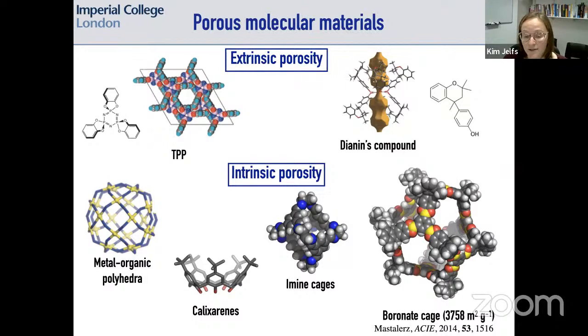There's various examples of this. What I'll be talking quite a bit about today are the imine cage systems, which in terms of purely organic systems are one of the most popular types of chemistry for getting to these highly symmetric cage-type molecules. Generally speaking, these molecules typically have quite low porosity, of the order of hundreds of meters squared per gram. So nowhere near some of the records of other types of extended network porous materials. But there is, I believe it's still the record holder as we speak, a boronate ester cage from Michael Mastalerz's group in Germany, which actually does have a very large cavity, as you can see from the image, but also quite a high BET surface area of over 3,700 meters squared per gram.